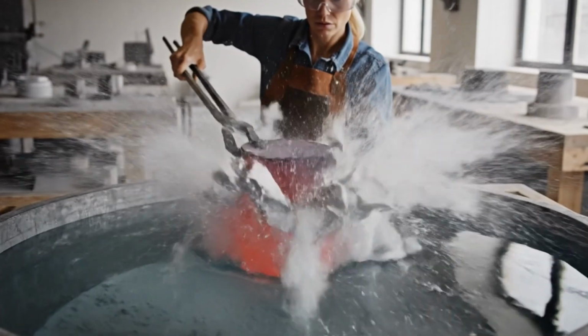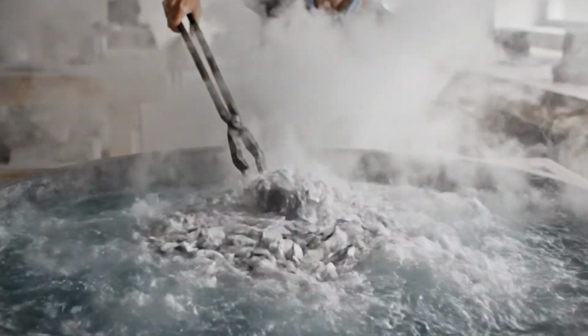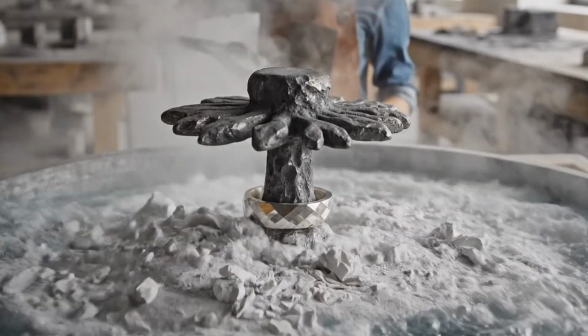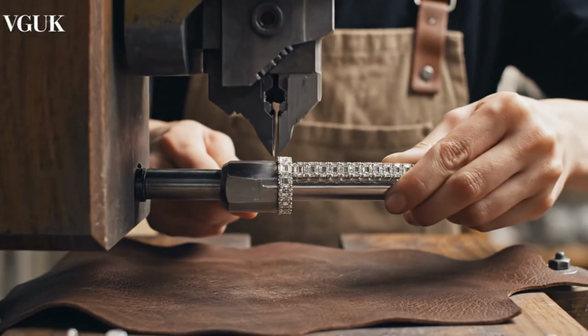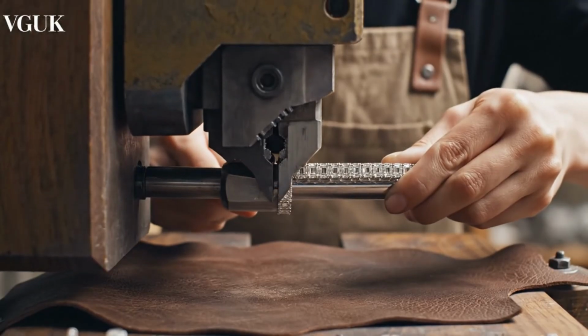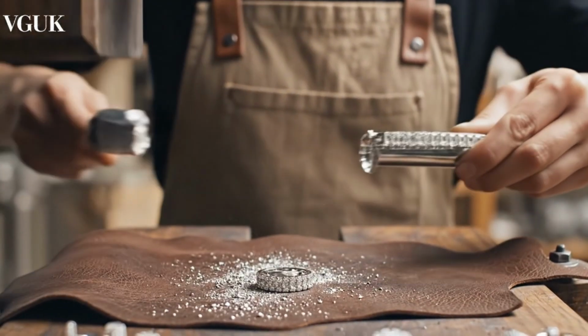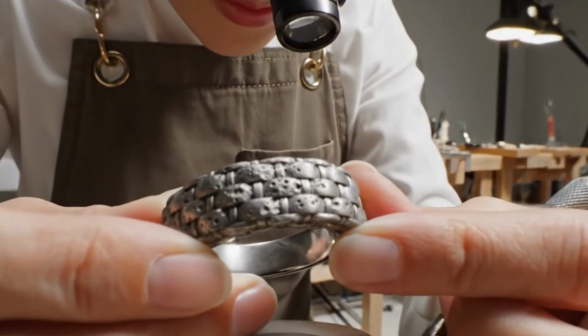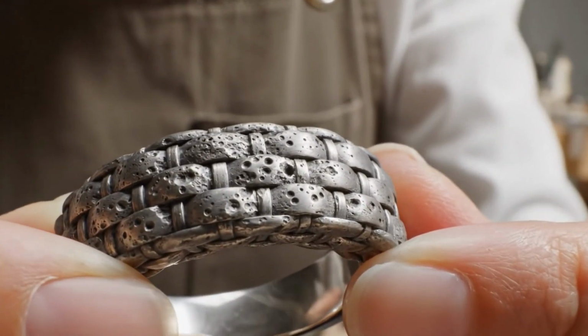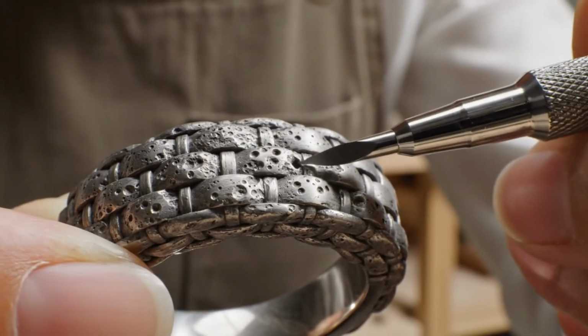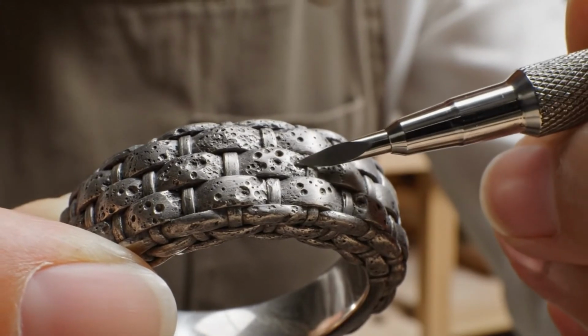We plunge the hot flask into water, the thermal shock shattering the plaster and revealing the dull gray metal tree inside. The hydraulic cutters snip the heavy feed sprue, separating the raw eternity band from the button that fed it during the cast. We inspect the raw casting for any porosity or air bubbles, knowing that even a microscopic void compromises the ring's structural integrity.